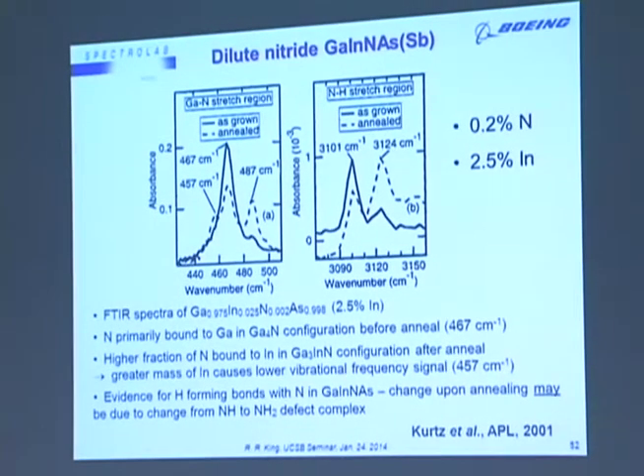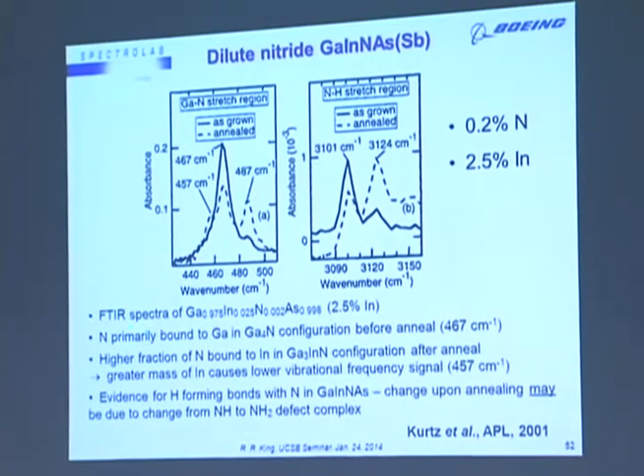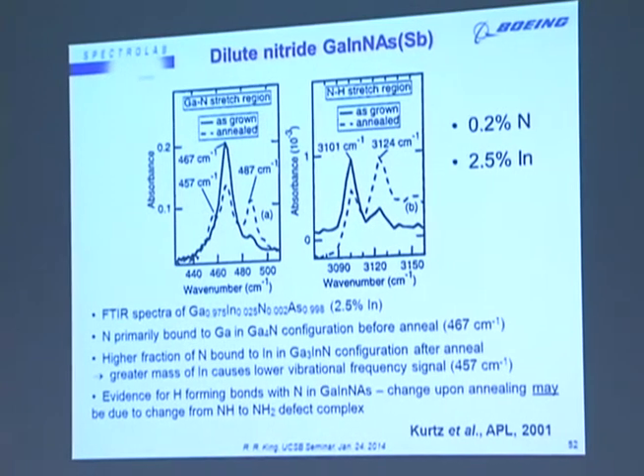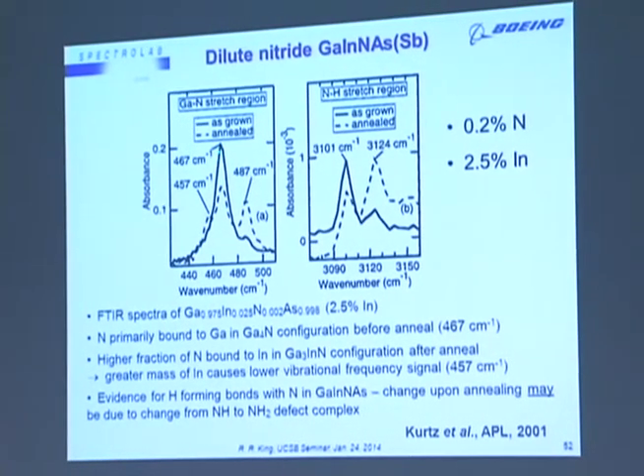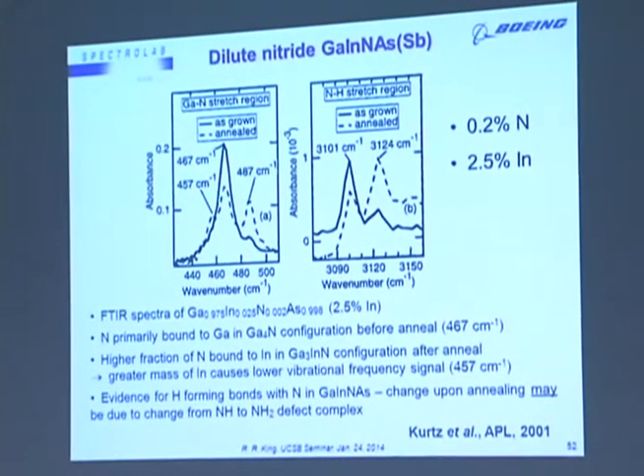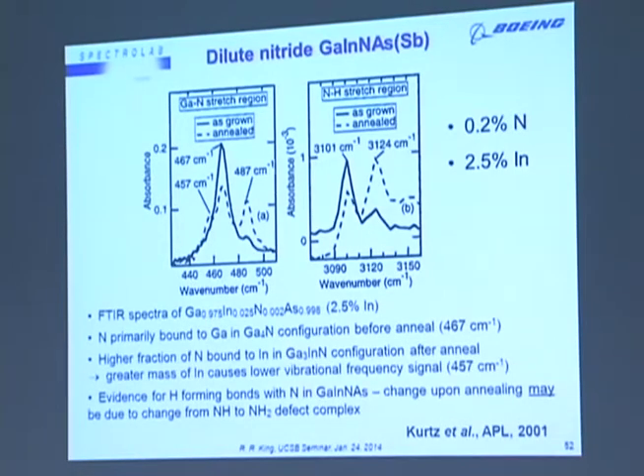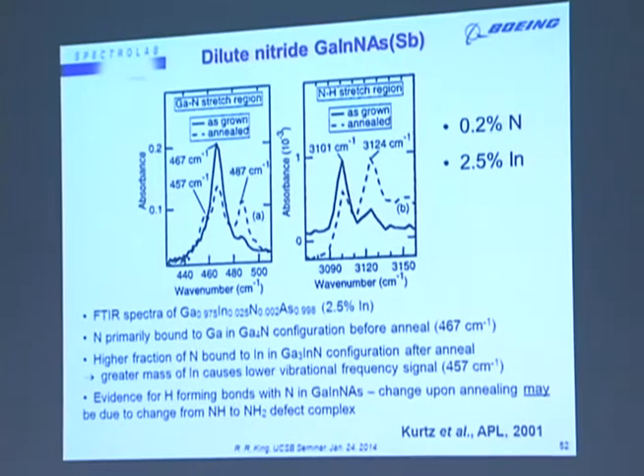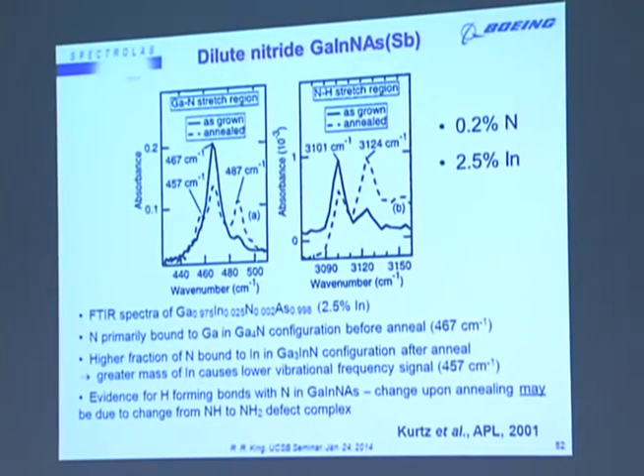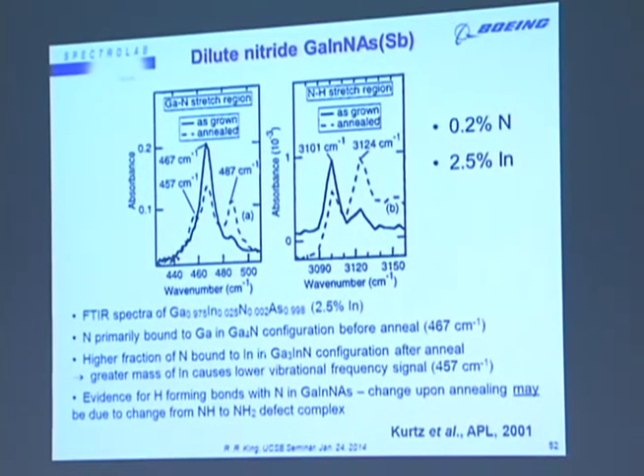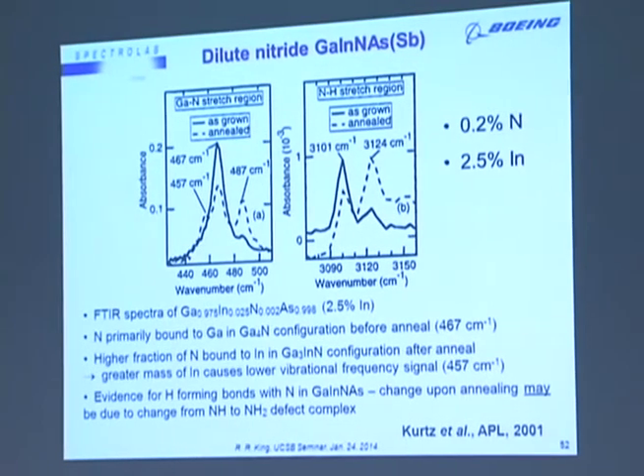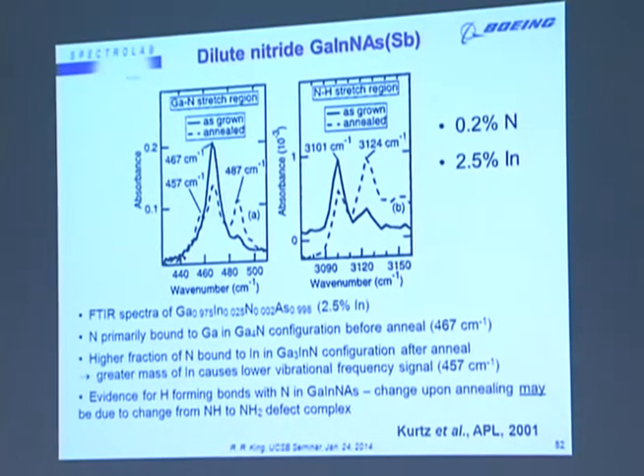One study that we did was on Fourier transform infrared spectroscopy of these defects in dilute nitride. And in this paper by Sarah Kurtz, we looked at these FTIR spectra. As grown, we see that this peak at 467 inverse centimeters corresponds to nitrogen bound to gallium primarily in a gallium-4 nitrogen configuration. However, after annealing, we see a higher fraction of that nitrogen being bound to indium in a gallium-3 indium nitrogen configuration. So that's very significant for the recombination in the material.